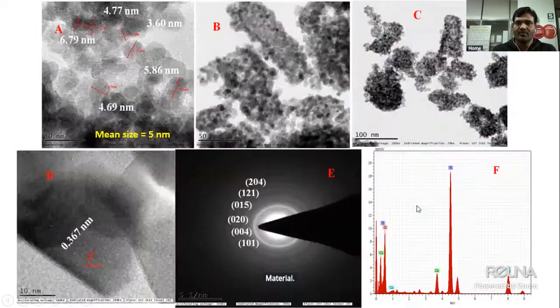Here we identify it by TEM analysis. TEM analysis gives the morphology of the material, so the size and shape of the material are identified. We can see clearly that the particles are spherical in nature. The average particle size is around 5 nanometer.